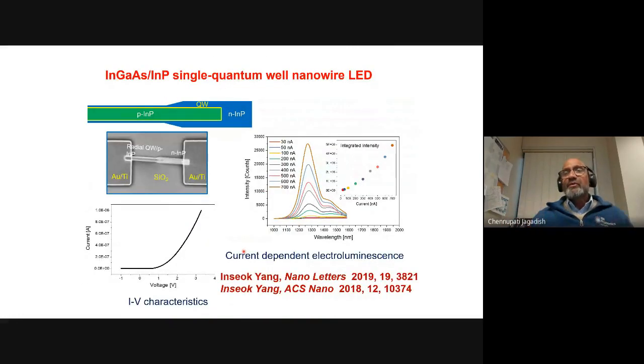So till now, I've only shown you the nanowires which are optically pumped. These are not electrically pumped, but ultimately industry wants to have electrically pumped nanowire lasers. Till now, by designing carefully and also by optimizing the growth conditions of various nanowires, we've been able to demonstrate optically pumped nanowire lasers. So if you want to make an LED or laser, for example, you need to do the doping, and we talked earlier about the P-type indium phosphide.